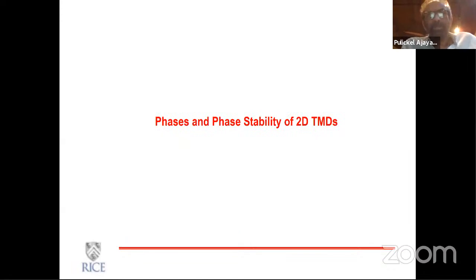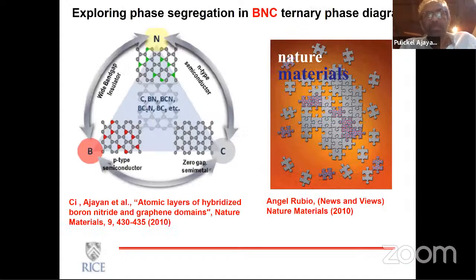Now let me talk a little bit about this phase stability that I mentioned in the beginning. Especially as you go to multi-component systems, you can see that the phases that form could be either segregated or mixed. I'll first talk about these segregated systems where you can form domains that are entirely separated but stay within the monolayer. And in particular, this phase diagram of boron, carbon, and nitrogen has lots of phases that follow this pattern.